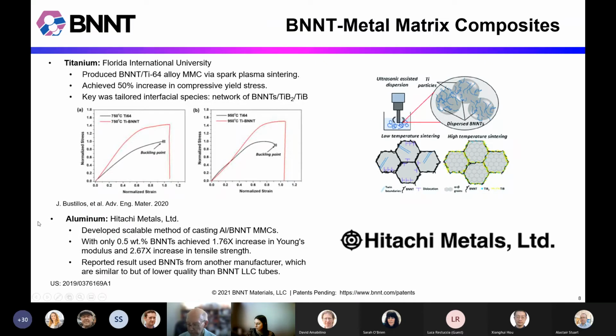And then also there's been some work on aluminum by Hitachi Metals in Japan. This comes out of a patent a couple years ago. This work was actually not performed with our boron nitride nanotubes, but I still thought it was interesting to include. Aluminum's of interest because of its low melting point. So they actually created a method to scalably cast a BNNT reinforced aluminum MMC and had some improvements in the modulus and tensile strength.